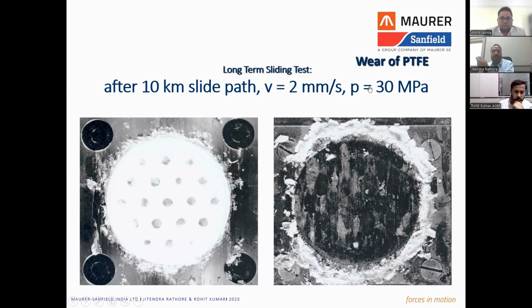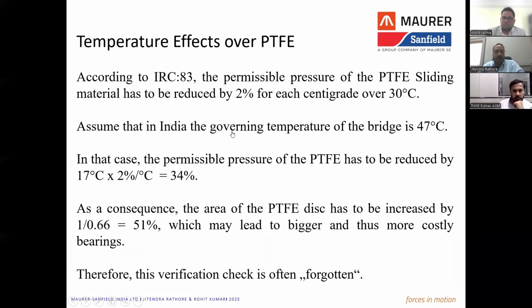And this happened when the stress concentration was 30 MPa and the velocity at which this test was performed was 2 millimeters per second. And if you refer to the EN standards, EN 1337 Part 2, which is for sliding material, you will find mentioned there that the total sliding path of PTFE is 10,242 meters only. That coincides with this value. In addition to that, there are temperature concerns. Why is it important for railway bridges? I included it here in this presentation.